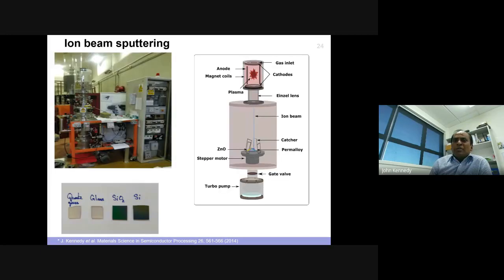So how do we make our thin films? We use a technique called ion beam sputtering. What it does is you have a sputter target. Let's say you want to make zinc oxide. You put it in a 15 kV argon ion beam.